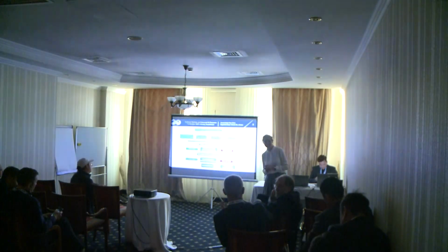And as Dr. Randy demonstrated from the field project with Dr. Marat, degradation may not be an issue in the field due to fractures. Perforation also: in the injector, if you have the information on the density of perforation, providing the available surface of injection, you have an apparent shear rate of degradation much lower than what you would imagine in the lab.